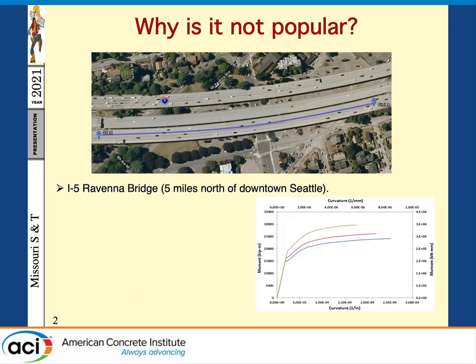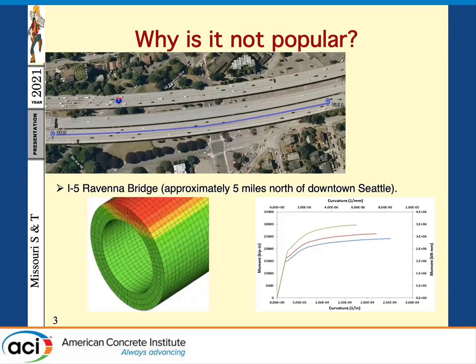When we did the moment curvature analysis for the cross section, it became obvious that the cross section is very brittle. The reason for this is shown here in a finite element analysis for the columns. You would see very quickly we reach an ultimate strain for the unconfined concrete from the outside over here. Recall that the spirals are at the middle.